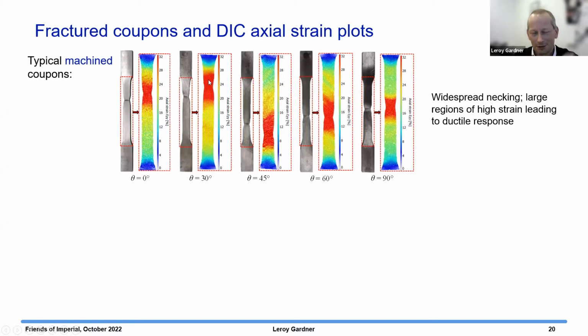And the red region is the region of high strain. And these red regions are quite large. And that means that the high strained zones are quite widespread, and that leads to a nice ductile response. And that happened in all directions, really, for the machined material.